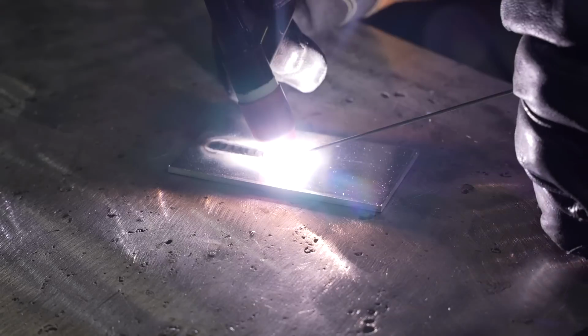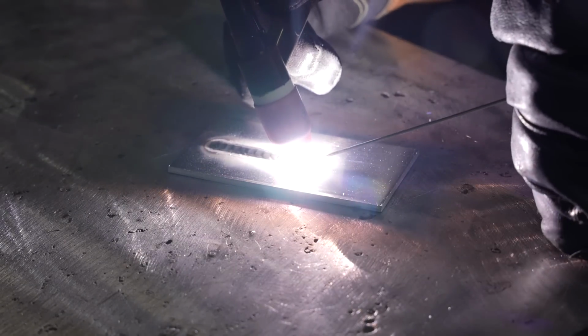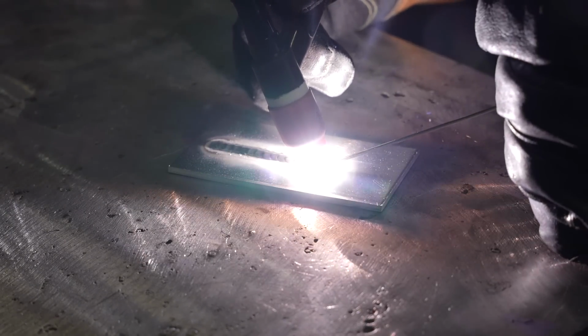Notice when I start the arc here, it's etching the oxide layer off, and it's a pretty wide etching band, and that's really the result that you get from using this cup that's a number 7 compared with a smaller, like a number 5. And that is not a problem necessarily unless the aesthetics are a problem from it. So it still works just fine. I get a nice clean bead all the way along and welds really nicely.